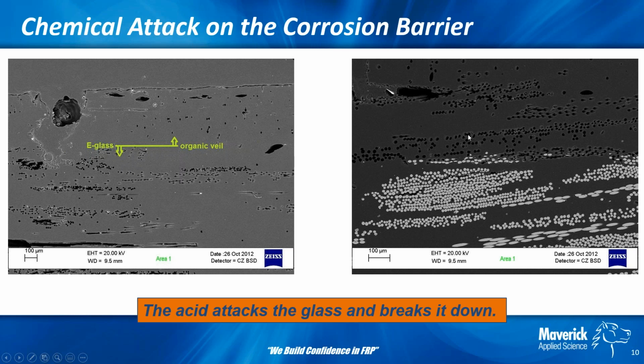If you look at the right-hand side of the slide here, this is a close-up of the chopped strand mat area. What you're looking at here, where you see all the black circles, that's where glass was. That's where basically our chopped strand mat layers were. And basically, this is e-glass. Again, this is going back to the late 90s, so ECR wasn't prominent at that time. I want to say around 95 or so is when Owens Corning came out with that, but it really wasn't used until probably close to 2000 on more of a regular basis.